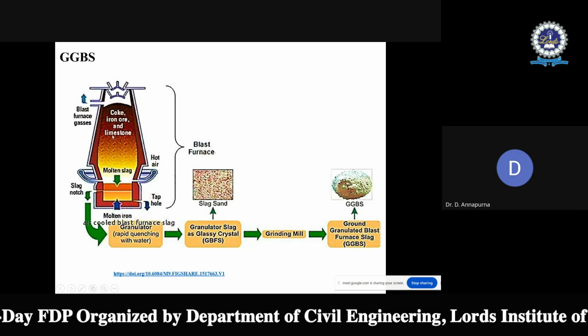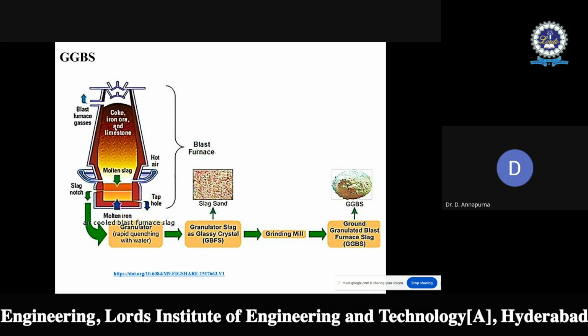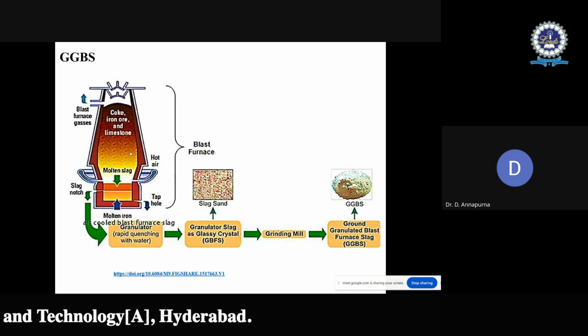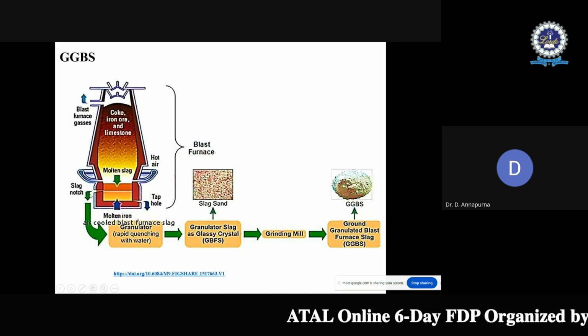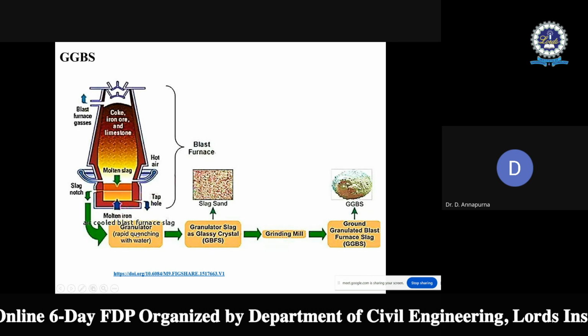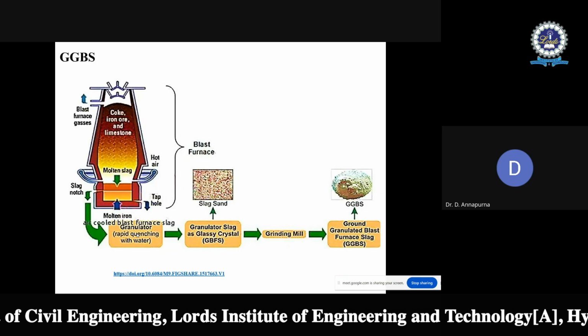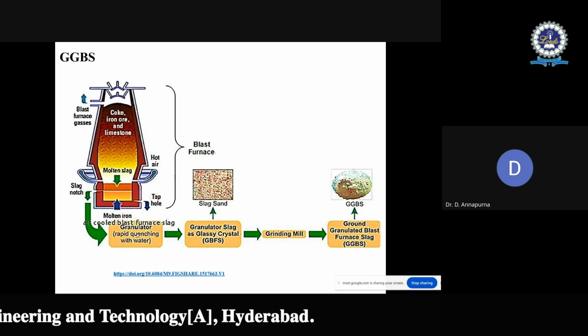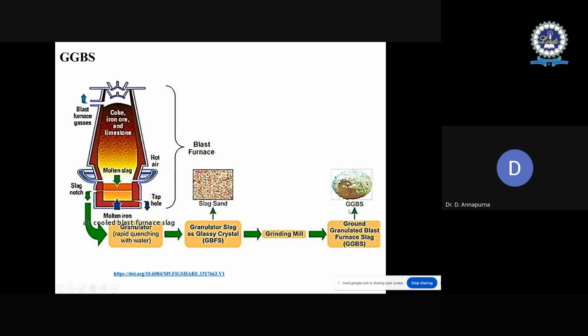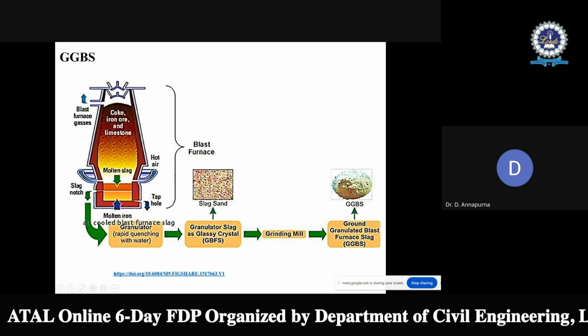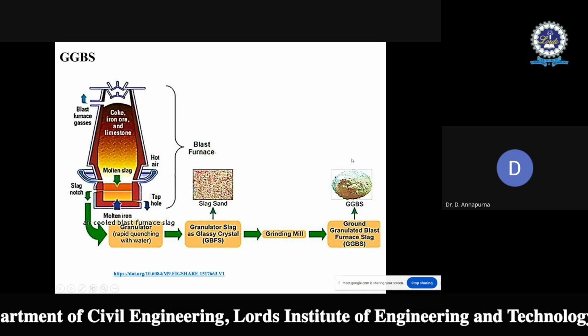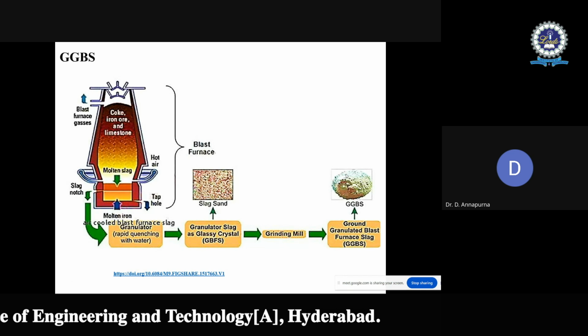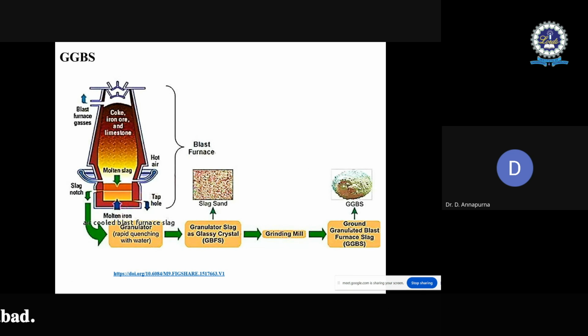Here coke, iron ore and limestone are fed inside the blast furnace and subjected to a high temperature. Then the iron ore is reduced to iron and the remaining materials form a slag. The molten slag is periodically tapped off as a molten liquid and rapidly quenched in large volumes of water. Then it is ground using a grinding mill and we get the ground granulated blast furnace slag. In between, slag is also taken out in a coarser form, which can be used as slag sand as a partial replacement for sand. But in the preparation of geopolymer concrete, it should be used as a precursor or source material, so ground granulated blast furnace slag is used. It is rich in calcium oxide, silica and alumina.